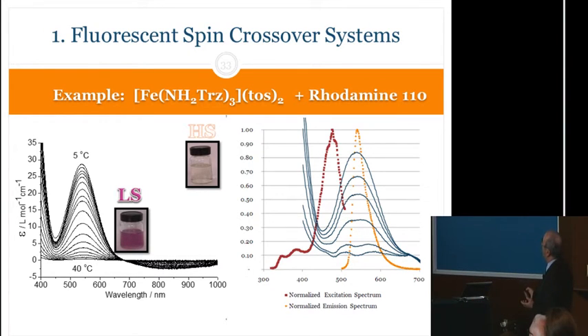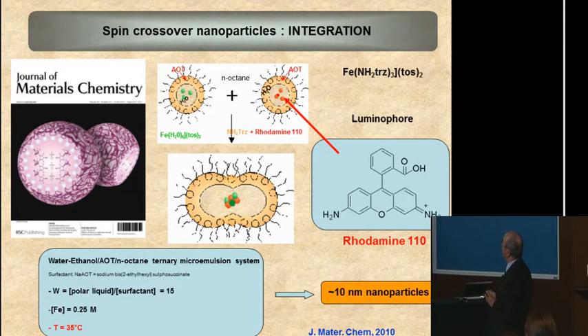So then, if you take the rhodamine, which is another complex, a luminescent complex, if you look at the optical properties of the rhodamine, you see that the emission of the rhodamine is exactly at 550 nanometers. What does this mean? This means that if you combine in the same material rhodamine and the spin crossover, if the system is in the low spin state, it will absorb the light of the rhodamine. But if it's in the high spin form, it's transparent, light is not absorbed. That means that through the spin crossover, you can quench or not the luminescence of your system. And you will see that through here, so then we did this synthesis, and Lionel also will explain how we can make these systems by combining the rhodamine here to make a hybrid system.